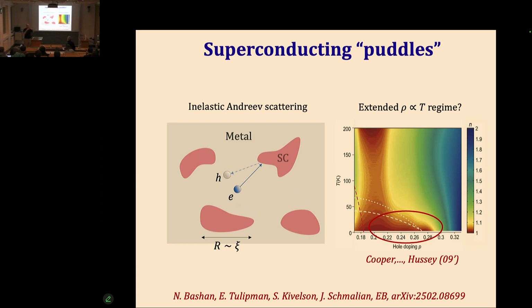You need the charging energy of these puddles to be significant. So basically, you'll start seeing this behavior only when the temperature is below the charging energy of a single puddle. Now, if you work out some rough estimates, that's not so small. You can have tens of nanometers, and the charging energy might be a few Kelvin. So you can still reach that. Now, the other requirement is that if you think about inclusions of a conventional superconductor inside a metal, you want to have a tunnel barrier between the two. If the interface between the two is too transparent, then superconductivity would be killed inside these metallic inclusions. But the best way to test this would be to construct an artificial strange metal using these kind of ingredients.